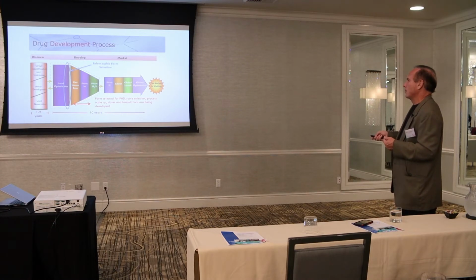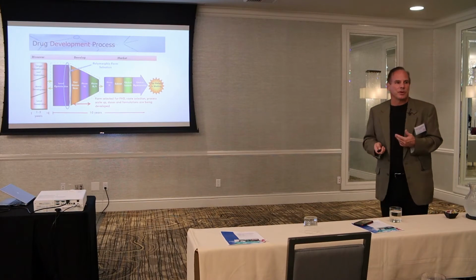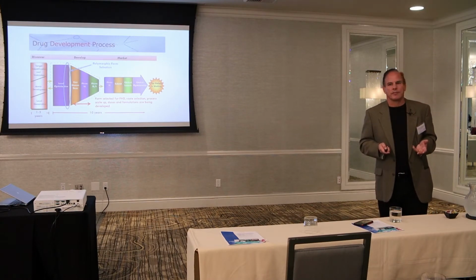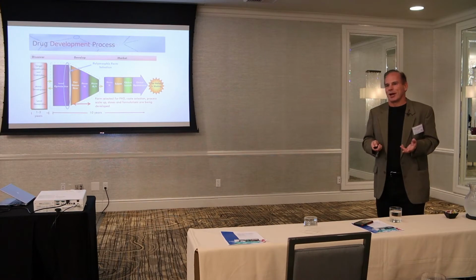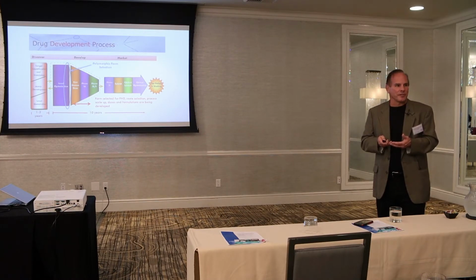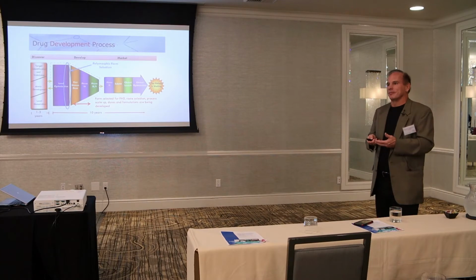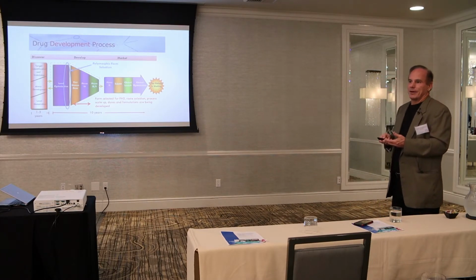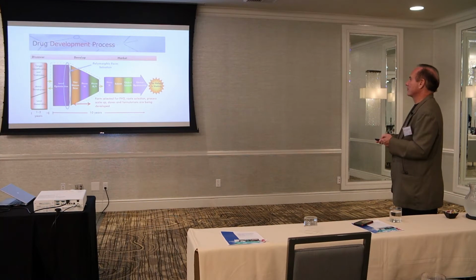And one important factor is route selection. Impurity profiles can change, and it's one of the most important factors in determining crystallization outcome. Because related substances are the most similar to the drug molecule, they're more likely to interact with the growing crystal form and what forms nucleate. And so it's an extremely important factor. The sooner you get your route selected, the sooner you can be more confident that you have the right physical form and that you've identified all of your polymorphs. So the sooner you pin down your chemistry, the better off you are.